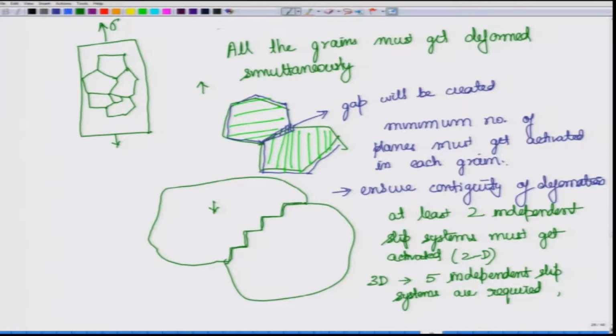So, 5 independent slip systems are needed to ensure contiguity of deformation and to ensure that all the grains get homogeneously deformed. We are not quantitatively deriving anything, but this is the basic information that you must have regarding deformation in polycrystalline material. In the second half of the course, when we touch upon plasticity, we will probably also describe this part in more detail. But for now, it is time that we move on to another aspect of glide,